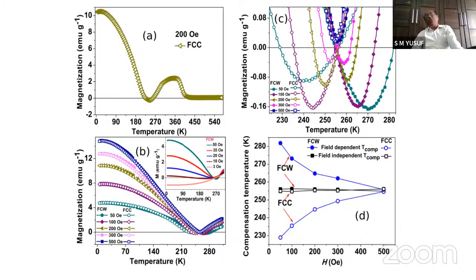And here I would like to point out only one observation, that when you do DC magnetization, let us say you see this curve, so-called B, if one is a little bit casual, you see magnetization, and like in a very old textbook, you will see this kind of so-called magnetic compensation. But if one is not very careful, one will be missing this fine structure, what is shown here. In fact, it passes through two zeros. So each and every curve passes through two zeros. And not only that, how you do the measurement, field cool warming or field cool cooling, this is a shift. And here I have summarized the compensation temperature as a function of external magnetic field. This one compensation temperature, which is here, does not change with field.